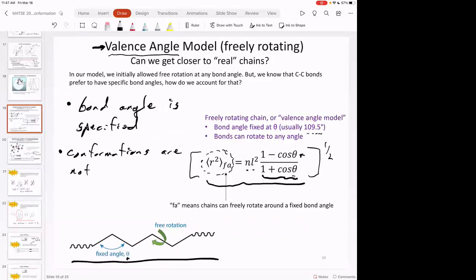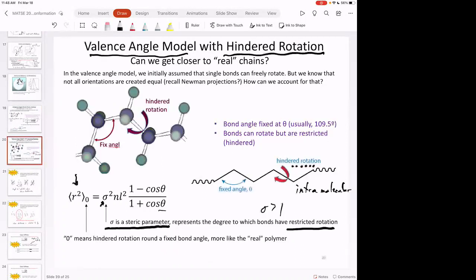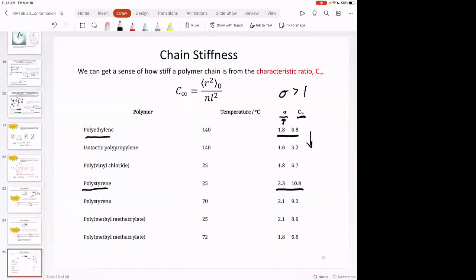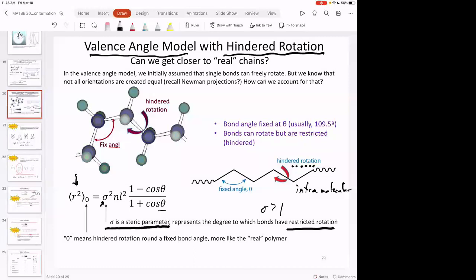And so we can say that the freely rotating valence angle model always underestimates the real length of a polymer chain conformation, right? This doesn't have sigma in there. We have the bond angle information. That's great. But the freely rotating valence angle model is always going to be less than the valence angle model with hindered rotation. We can't think of a simpler polymer than polyethylene in this model. And so if the steric parameter and characteristic ratio are greater than 1, even for polyethylene, that means the most accurate model that we have so far is this valence angle model with hindered rotation. This is as close to reality in terms of polymer conformation as we're going to get. Everything else is more and more idealized.